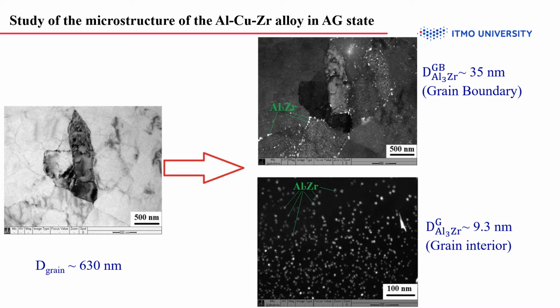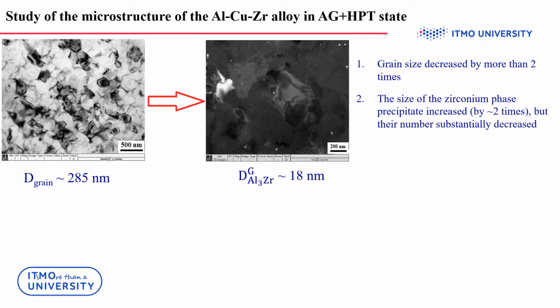The highest electrical conductivity of the studied alloy, 54.8% IACS, was achieved by purification of the aluminum matrix from solute alloying atoms in the process of artificial aging. HPT processing led to the formation of a UFG structure with an average grain size of 285 nanometers.